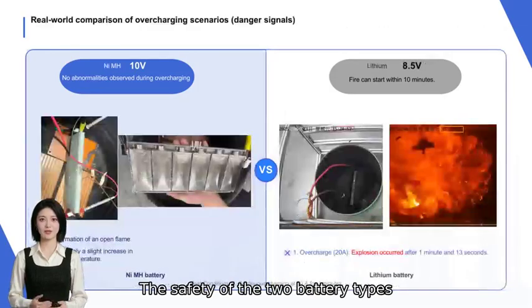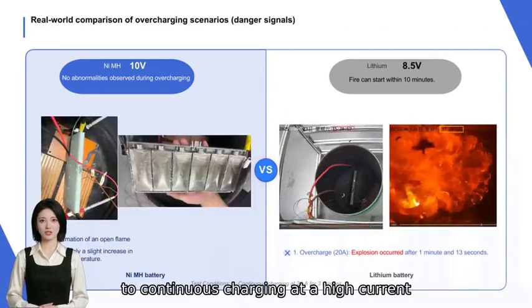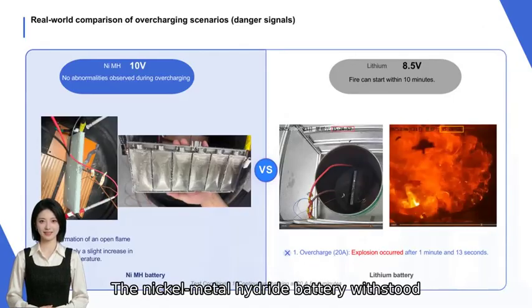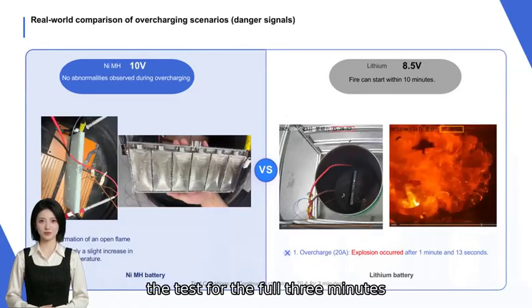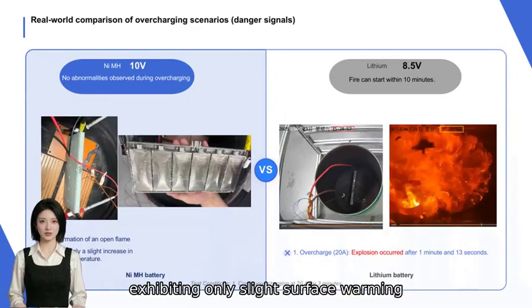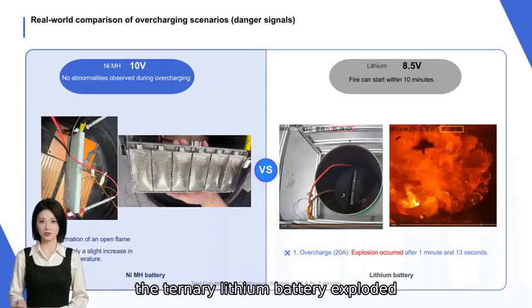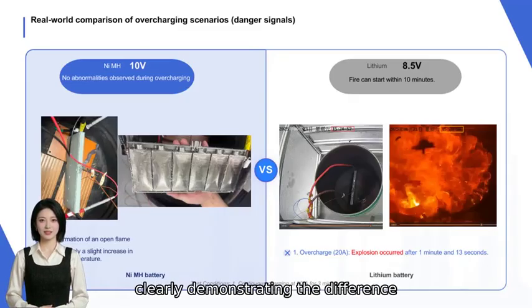The safety of the two battery types was tested by subjecting them to continuous charging at a high current of 20 amps. The nickel metal hydride battery withstood the test for the full 3 minutes, exhibiting only slight surface warming throughout. In contrast, the ternary lithium battery exploded after just 1 minute and 13 seconds, clearly demonstrating the difference in safety.